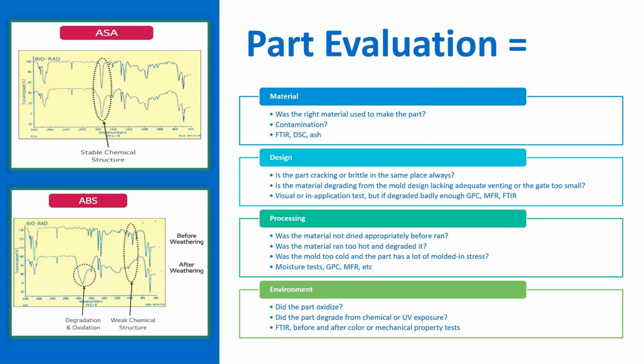Processing: was the material not dried appropriately before we ran it? One of the tests, as I mentioned in my fourth bullet that I didn't really go over, would be moisture analysis testing. So is it a material that needs to be dried? Did we dry it? Because if we didn't, that's probably a big problem. We tend to find that one of the number one culprits is that it's a material that needs to be dried and it was not dried appropriately.